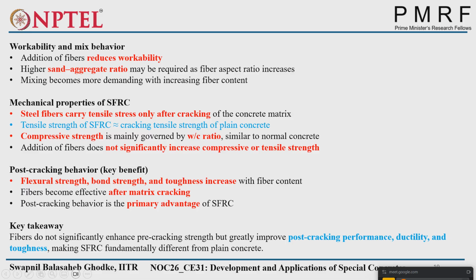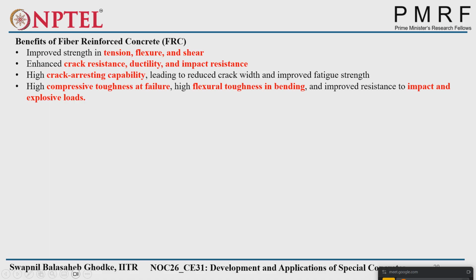So what is the key takeaway from these observations? Fibers do not significantly enhance pre-cracking strength but greatly improve post-cracking performance, ductility, and toughness, making steel fiber reinforced concrete fundamentally different from plain concrete. So how we will see,